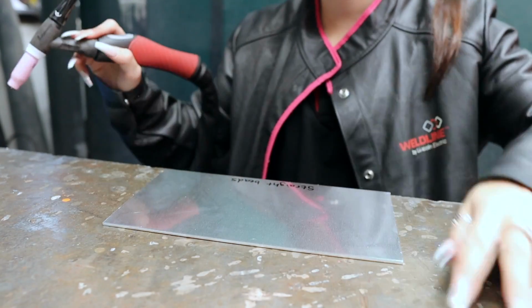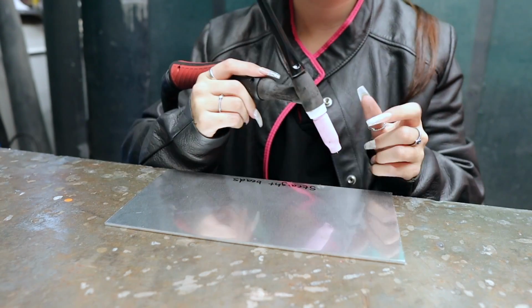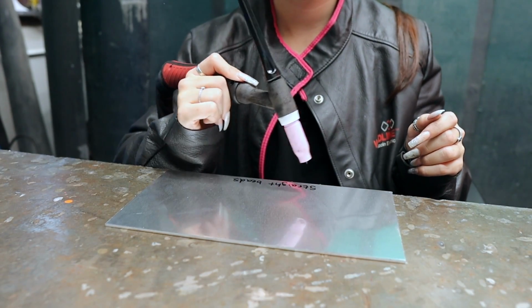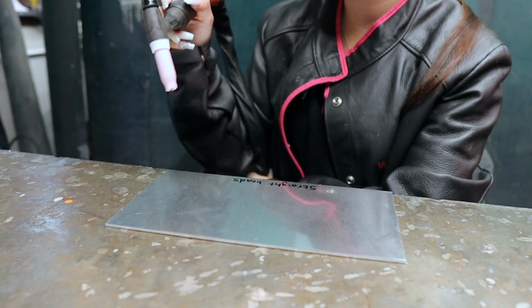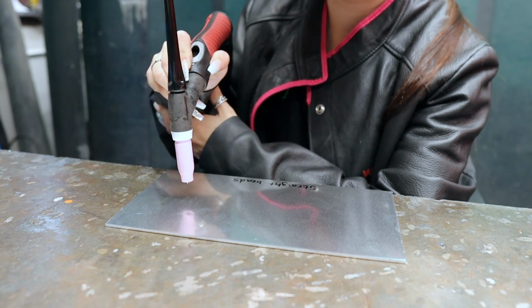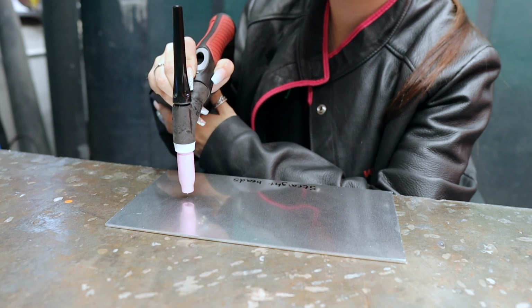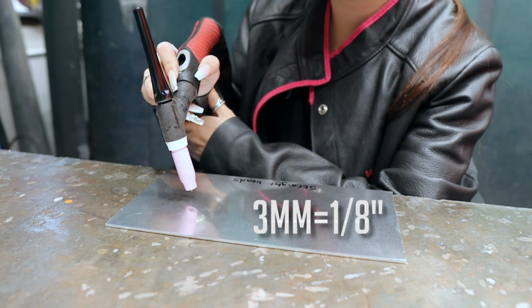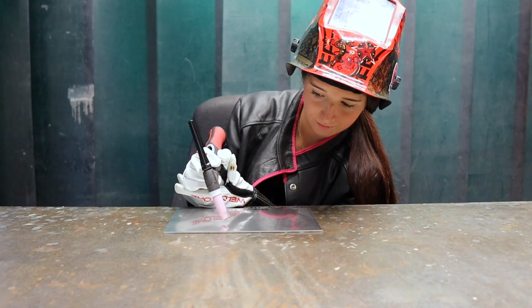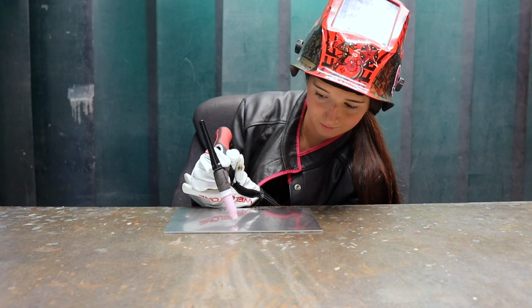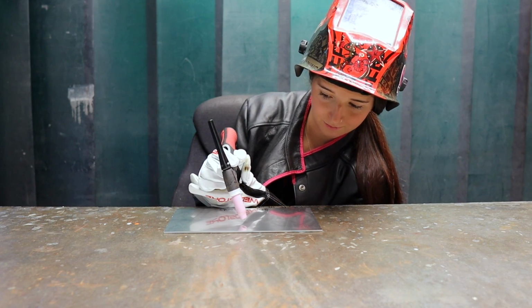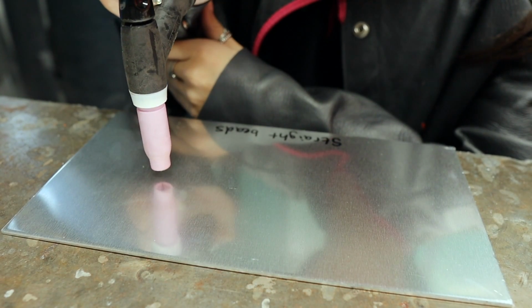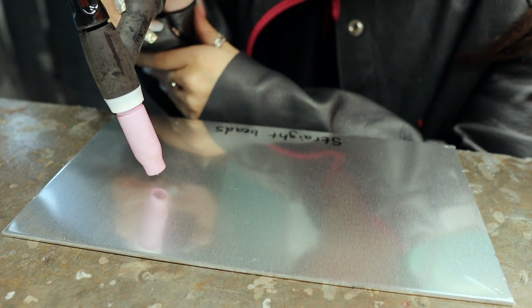When using the TIG torch, you use a push motion, leaning the torch back around 15 degrees from vertical. This means you're able to see the weld pool, but you have to keep the tungsten about 3 millimeters away from the weld material. If you dip your tungsten in the weld pool, you contaminate it, which then contaminates your weld. So what you need to do if this happens is resharpen your point on your tungsten.